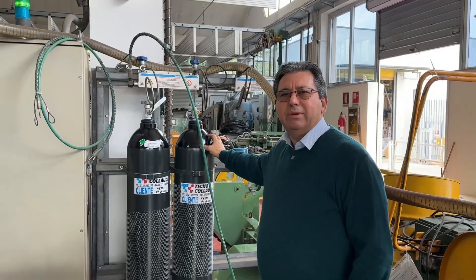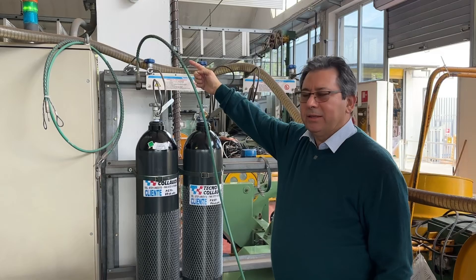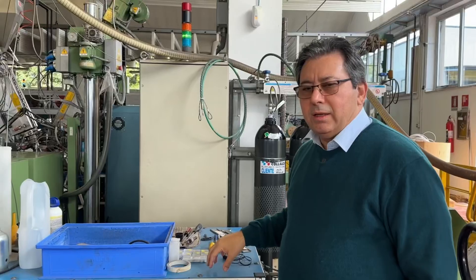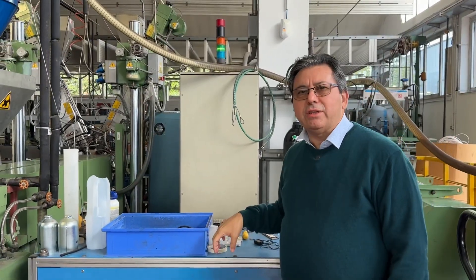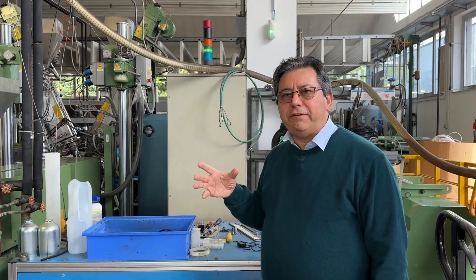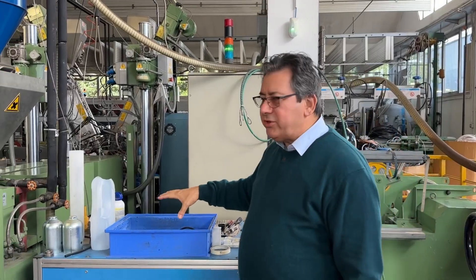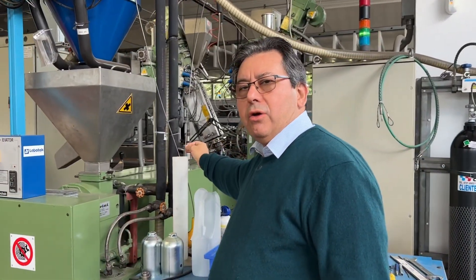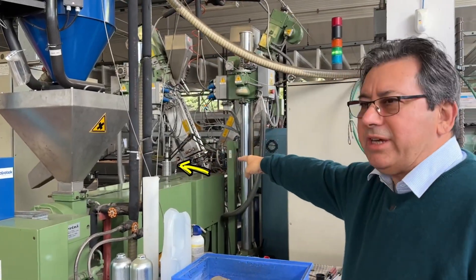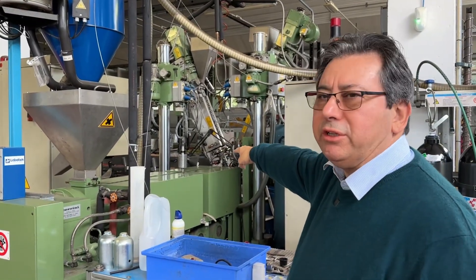You can see here there are some nitrogen gas tanks. From the tanks, the gas is brought by means of a tube inside the machine, where we increase the pressure to several atmospheres — up to 250 atmospheres. It's a very, very high pressure. Through a small iron tube, it goes into the extruder where you see the heat sink, right in the middle.